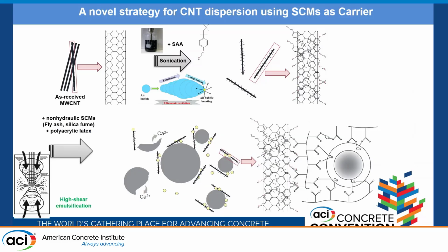So we started wondering what we did wrong. And here is where we started figuring things out, by adding a high shear emulsion process, where the emulsification uses a high-speed mixer, and the vortex process goes through all the SCMs and latex particles. It's a physical process, but really, I think what happens there is that it forces the interaction between the surface of the carbon and the latex, and most importantly, you start to break up some of these SCM particles. I think Professor talked about this before. It releases metal ions into the solution. That's really the cross-linking agent that's needed in the process.